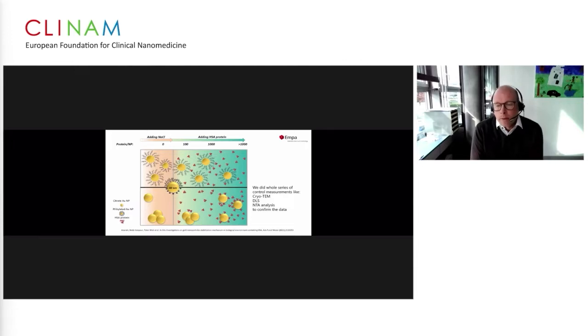blood. This data we, of course, tried to verify with cryo-TEM analysis, DLS as well as it could, and NTA analysis, and we got a consolidated picture that with the SAXS measurement and this microfluidic device, we are actually able to discover this early event.